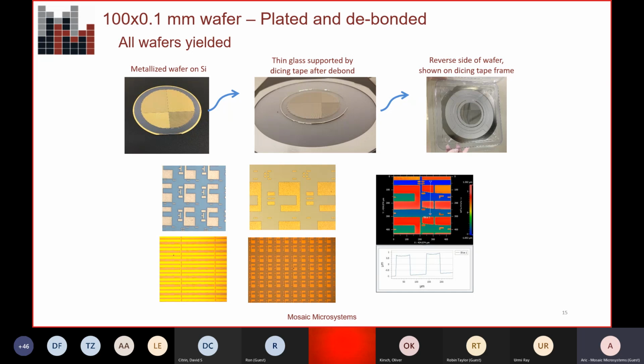But what's really exciting about this one is we bonded 8 or 10 100 micron thick glass wafers to a silicon handle, gave it to Micros. They did a little bit of development on the lithography optimization, but came out with very nice features down to 6 microns. They plated 8 wafers. They did the litho on 8 wafers. We debonded 8 wafers, and then we diced 8 wafers. So we really didn't have any breakage processing these 100 micron thick wafers. Granted, they were 100 millimeter diameter, but still, no engineering development, just taking these wafers, putting them through plating and lithography and debond and dicing, and had very good success.